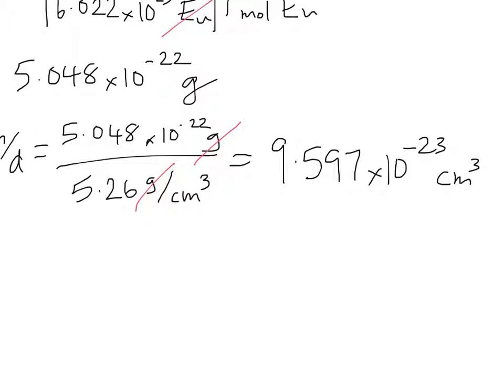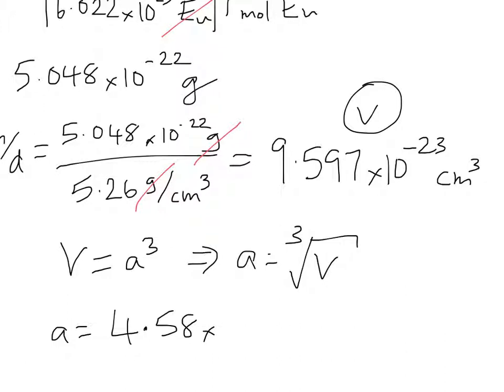Alright. What were we asked for in the problem? We had to find a, the length of the unit cell. And of course, we know that for unit cells that are cubic, a cubed is the volume. So now we've just named the volume. So if we want to find a by itself, we just need to form the cubed root of the volume. And so if we take the cubed root of our number above, we get 4.58 times 10 to the minus 8.